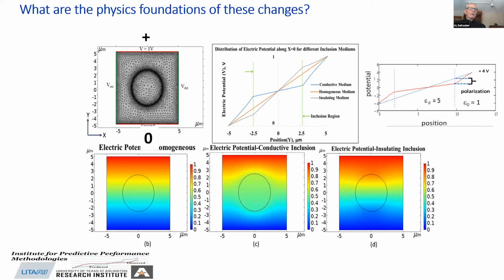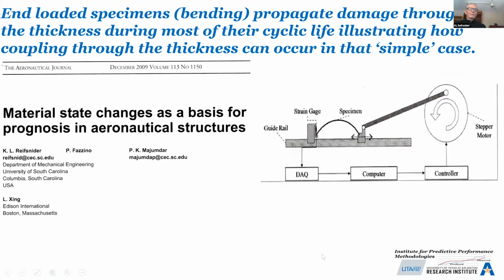And that's interesting. And if some material inside there is more insulative, less conductive than the center section, the slope will be greater because the change in voltage must be greater to make that thing constant if the other quantity is going down. So what happens at the interface? There is an abrupt change of voltage, rate of change of voltage across that interface, which is, by classical definition, a charge, a collection of charge, a polarization, if you will, as shown on the top right. We've done these experiments, we know it works, and so we can use this as our starting point.